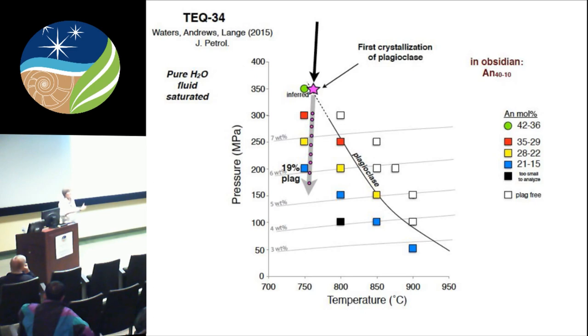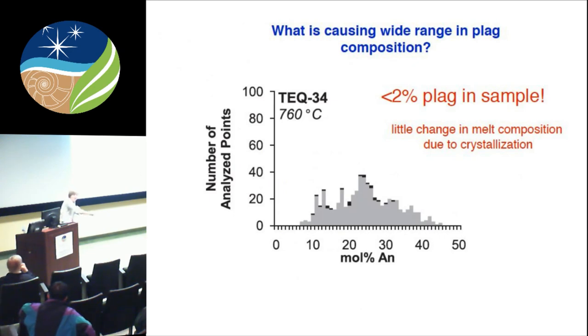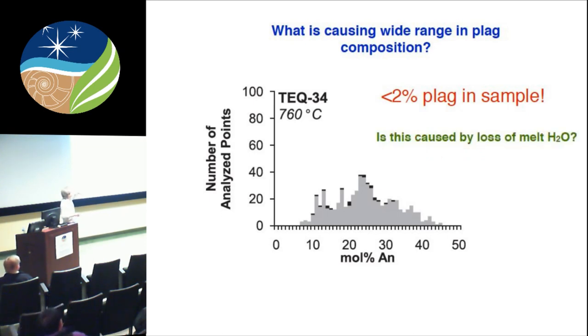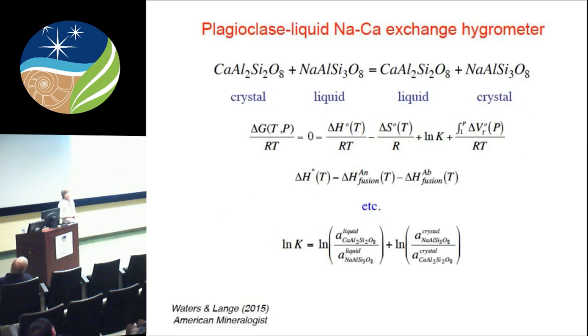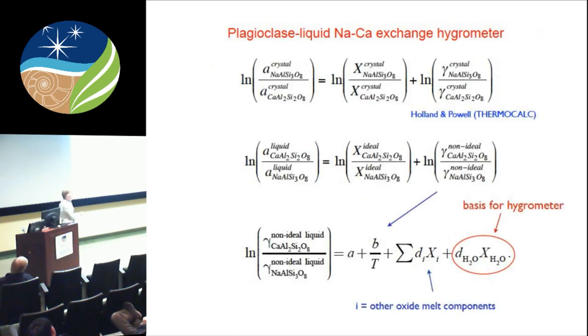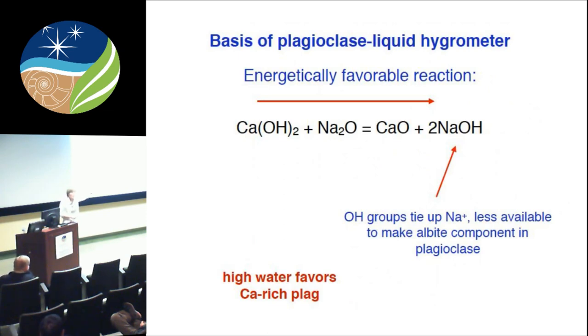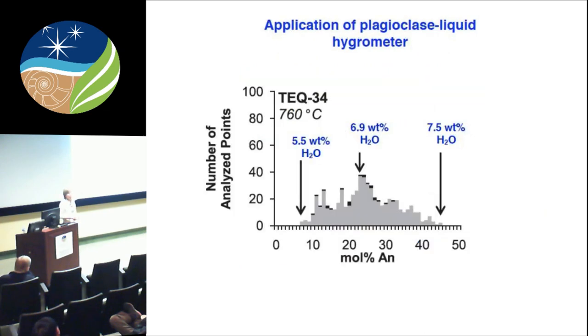And so the first question is, how do you get such a wide range of composition? Because it cannot be due to the effect of crystallization changing the melt composition. So it has to be something else. And could it be due to a loss of dissolved water in the melt? And it's well known that this exchange reaction depends very strongly on dissolved water content because of the activity composition relationships here. We think, it's our hypothesis, that dissolved hydroxyl groups preferentially complex with sodium relative to calcium, which lowers the activity of albite and makes a more calcic plag. Irrespective of the mechanism, it's well established experimentally. So when we apply the hygrometer, we can explain this variation with just loss of water.